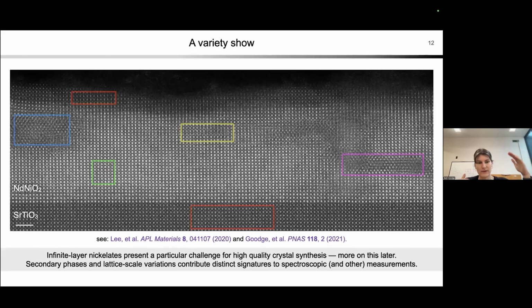But in all these other colored boxes, there are regions which are something else, right? So the two red boxes kind of above and below highlight just the substrate. So the sort of platform that the material is actually grown on. All of these superconducting nickelates are grown as very thin films. You can see it's only about 10 nanometers thick. So you have to grow them on top of something else. In this case, it's the strontium titanate material.